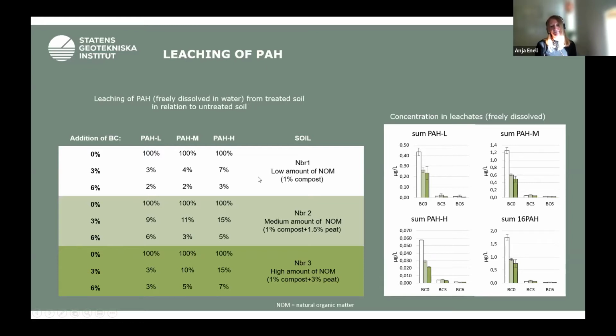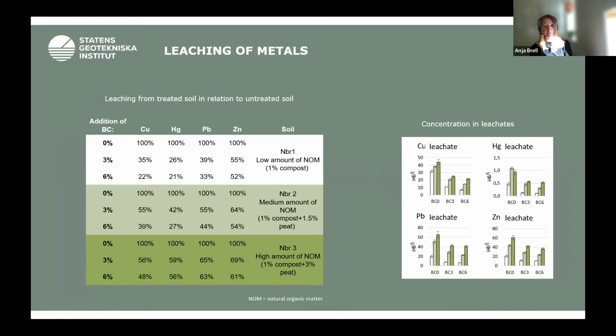And you will get the highest reduction if you treat a soil that has a low amount of organic matter. So if you look here at the number 2 and number 3 soil where we have additional peat, the reduction is not so drastic like in the first case here, but still it's a very good reduction. And we received the same pattern for metals, but not equally as good as for the PAHs. Here we were able to reduce down to 35%, for example, when we add 3% of biochar, and down to 22% when adding 6%. But again, the same pattern. When we are trying to treat a soil that has a higher amount of organic matter, you get a less reduction.